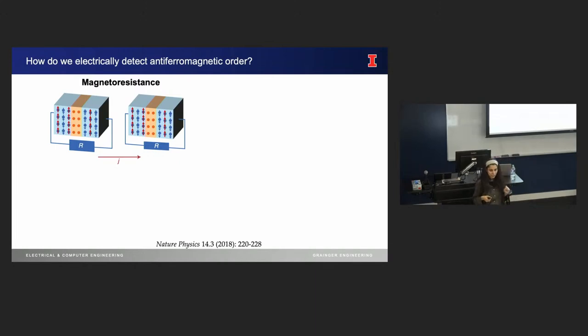Now, there are some spintronic phenomena that are available to read the antiferromagnetic state. So first is magnetoresistance. What does this do? You take two antiferromagnets and you sandwich them, and there is a thin tunneling barrier in between. And depending on the orientation of the antiferromagnet, you might get a low resistance or a high resistance. Now, you might have imagined that this is only theoretically possible. It has not been experimentally demonstrated in pretty much all of the antiferromagnets that we know of, except last month, a paper came out in Nature which demonstrated the magnetoresistance effect in manganese tin, which is a material that I will talk about today. So that's the only material in which this has been experimentally observed.